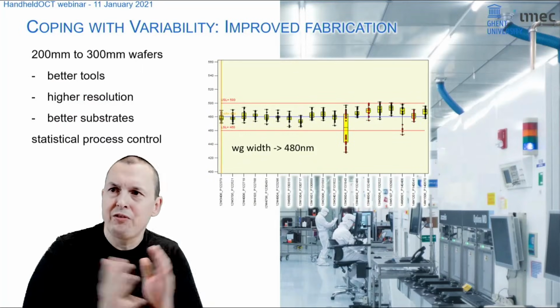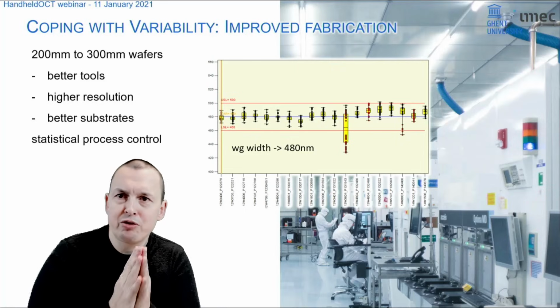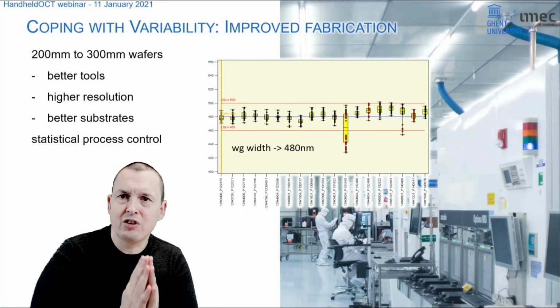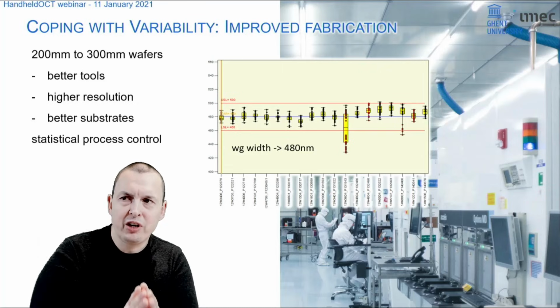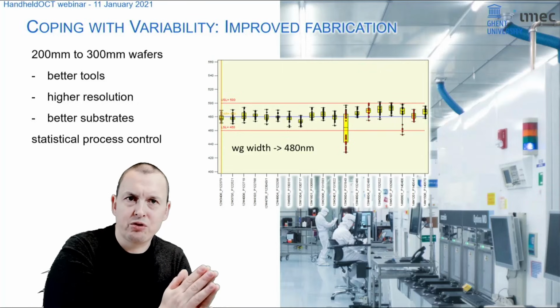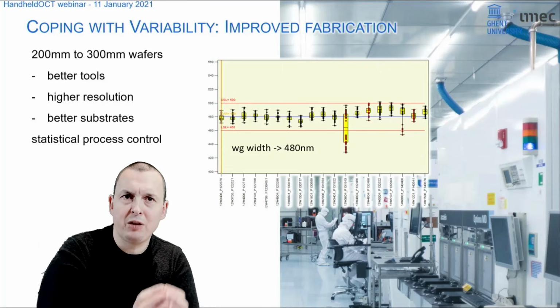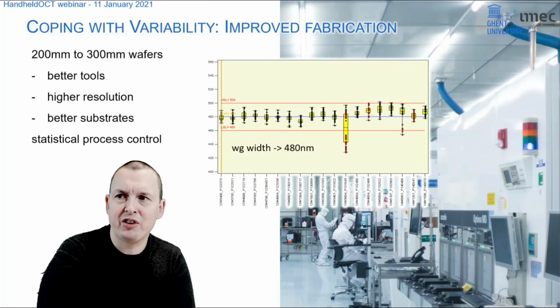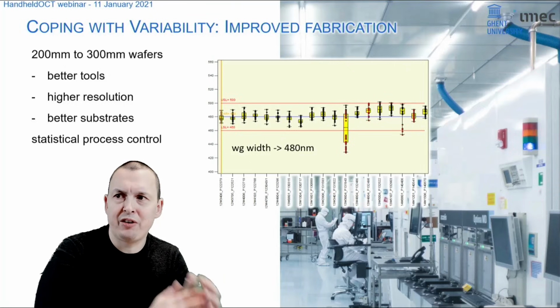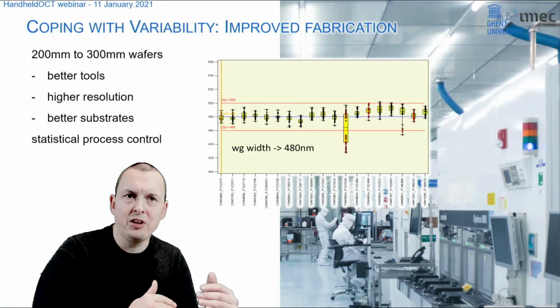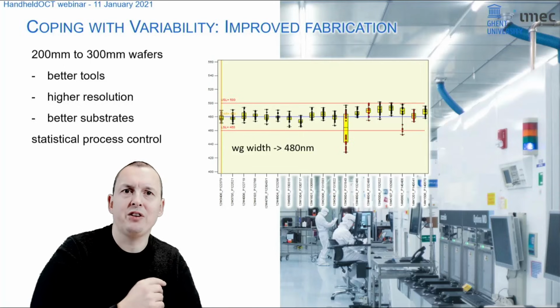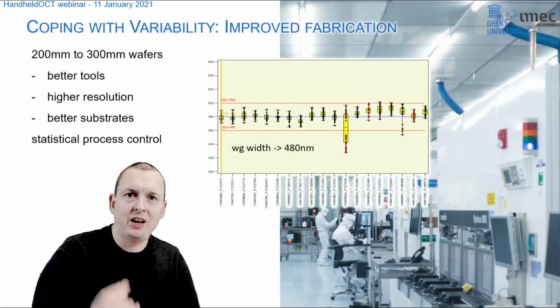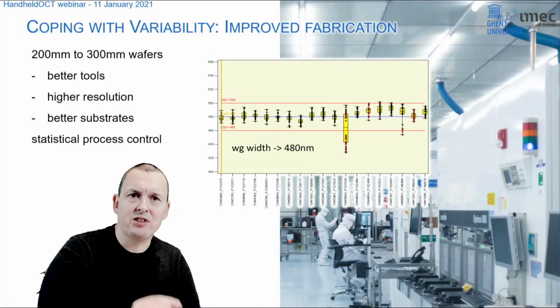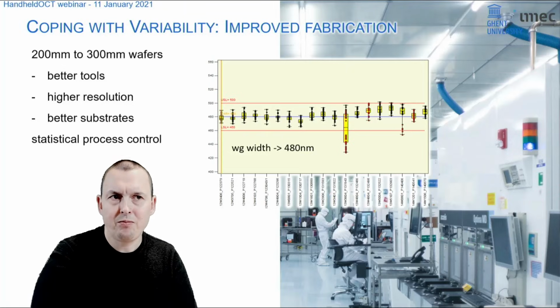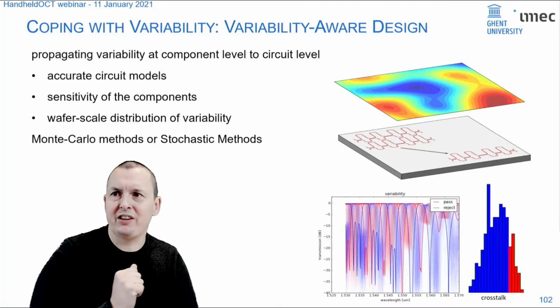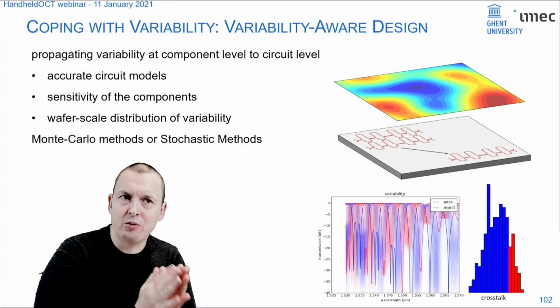So, if you want to cope with variability, first of all, improve fabrication. This is something that's continuously ongoing. So you can go to better fabrication tools, which typically means moving from 200 millimeter to 300 millimeter wafer fabrication, which has better lithography, better etching techniques. You get higher quality substrates with better uniformity of your layer thicknesses, and you really introduce very stringent statistical process control.